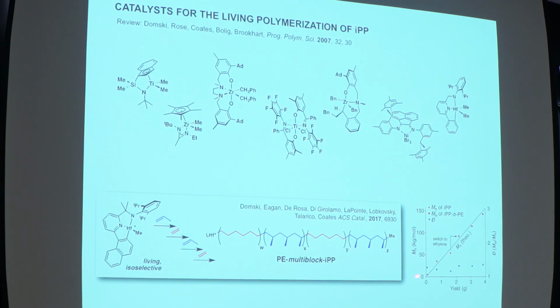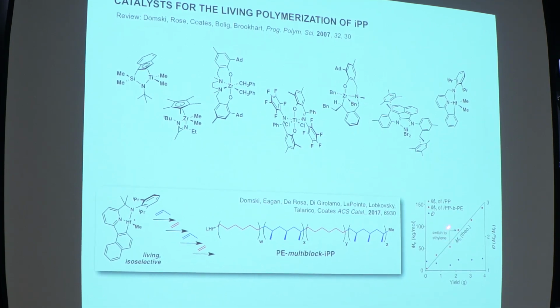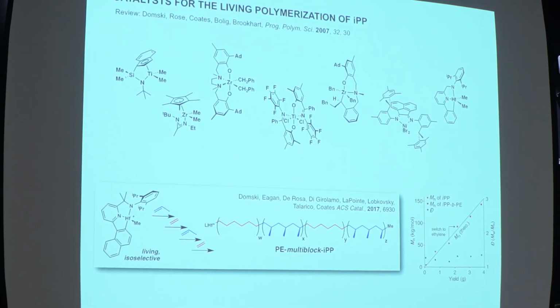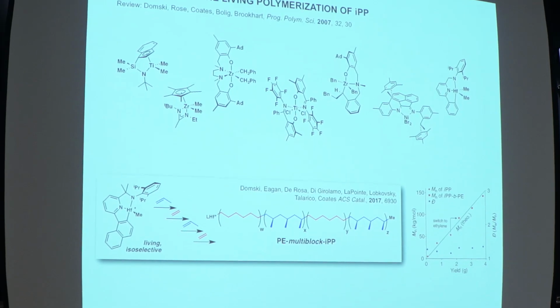If you're in the field of polymer chemistry, you know that there's this living plot. And so here is, as we make polymer, the molecular weight grows linearly. And here's a diblock where we swap to ethylene halfway through with overall about 150,000 molecular weight. So these are large molecular weight polymers.